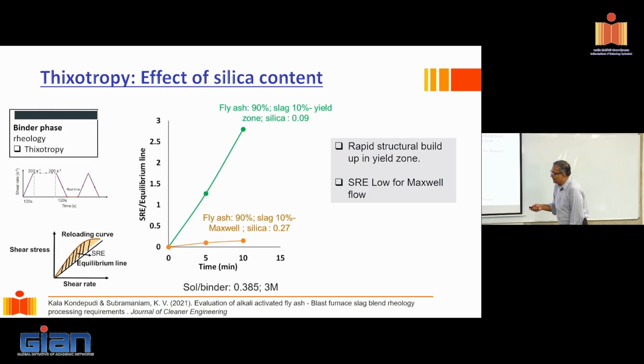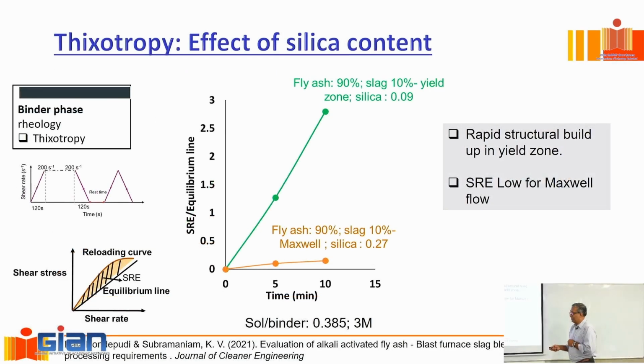What I'm showing you here is the ramp up, ramp down data after I've done this here, where I've completely smashed the structure. Now, this area between this is basically the energy that would take to break the structure, which has been smashed. So it gives me an idea of restructuration that's happening inside the fluid, right? So this SRE that I measure with different time intervals. So this interval that I have here, if I increase, what's going to happen? I expect structuration to increase. So we measured the structuration in a mixture where I have fly ash and slag at 90 and 10 with 9% silica and 27% silica.